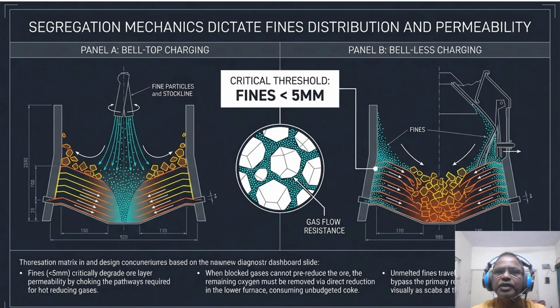And as an operator, we all know it's pretty clear when gases cannot reduce this ore in the stack, that oxygen must be removed via direct reduction in the lower furnace, consuming unbudgeted coke and driving your fuel rate. Furthermore, unmelted fines traveling the wall path appear as a scab at your tuyere pipe sides, signaling a loss of control. While fines physically block the gas, the moisture riding on those fines creates a secondary invisible thermal barrier.